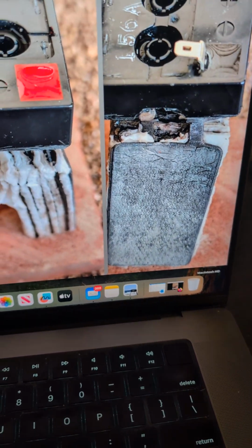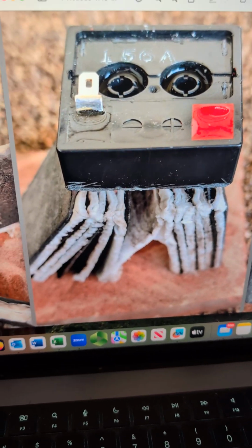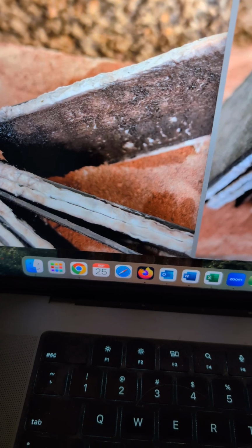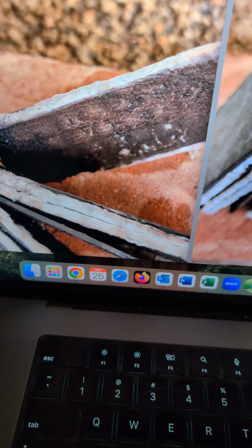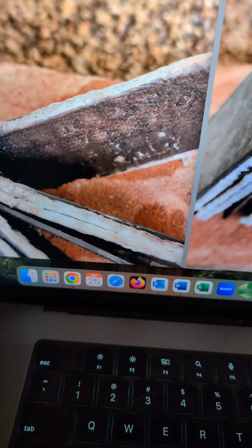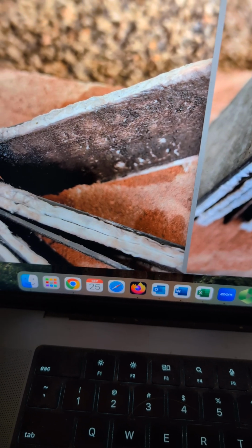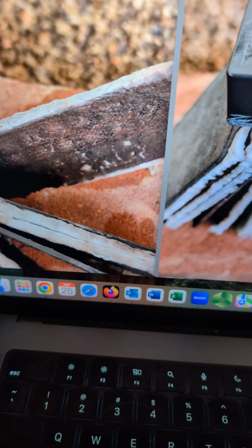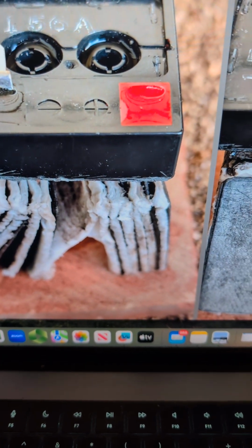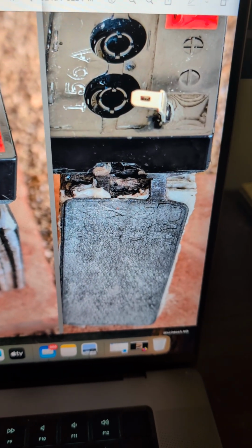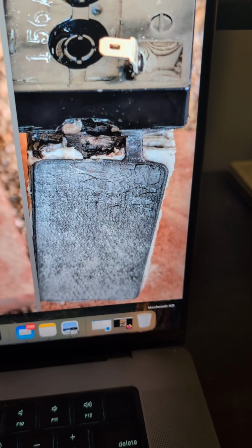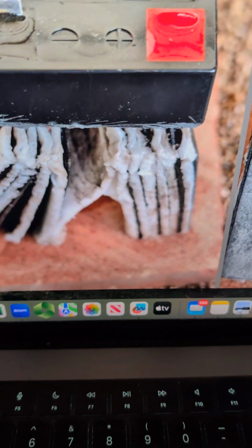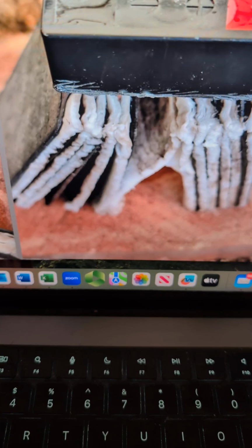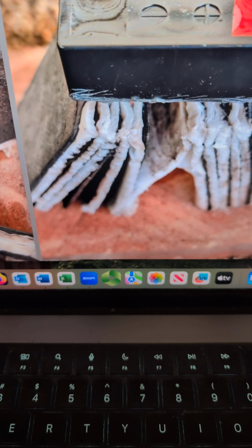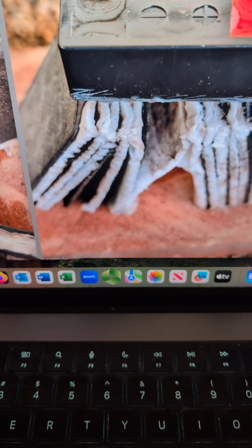These are very good cells, batteries for good value. And we're doing cycles of charge discharge with some of them, try to go to 100, 200 cycles, and then once again take it apart and examine the lead sulfate crystals. Hopefully they're small, and it's the larger lead sulfate crystals that kill a lead battery. So we want to examine that. We're also going to study the glass fiber paper, analyze it, take a look at what it looks like at 10 to 50,000 times magnification.